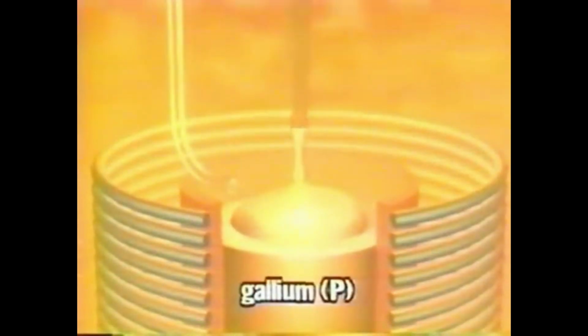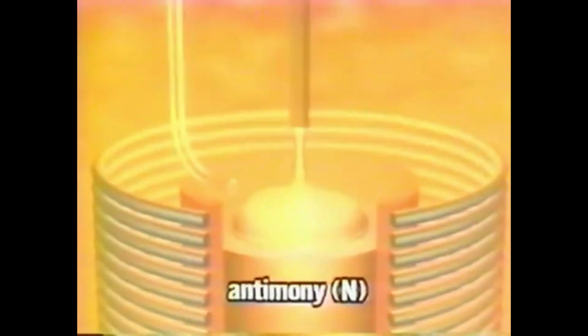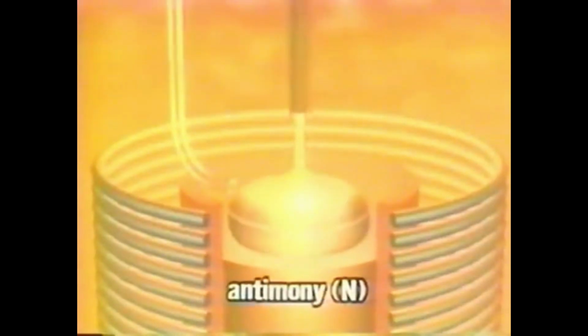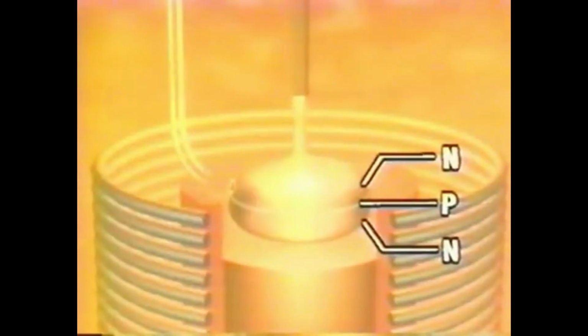Here's how grown transistors are made. During seed crystal production, p-type impurities, in other words electrical elements with positive properties such as gallium, are dropped in. The gallium then forms a melted-in layer in the growing crystals, which become a p-type layer. After about 10 seconds, n-type impurities such as antimony are then dropped in, so that another n-type layer is grown below the p-type. The crystals thus form an NPN sandwich.